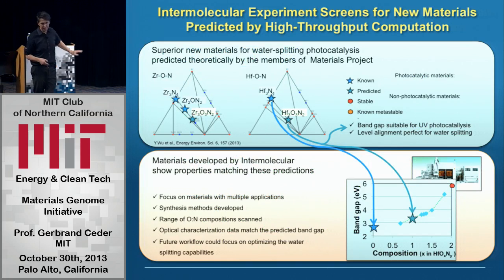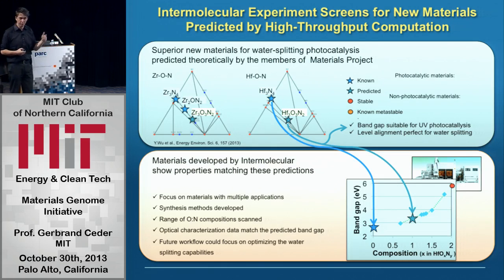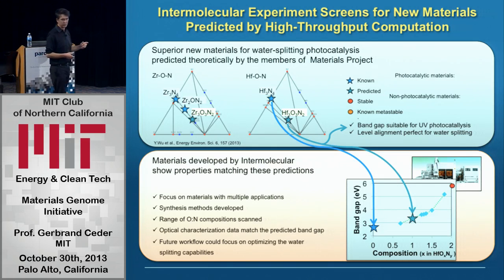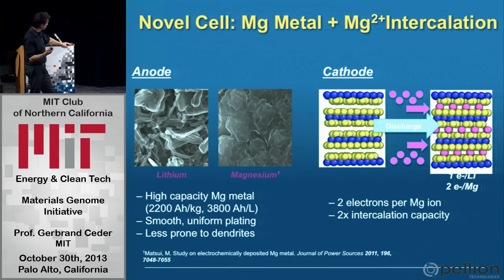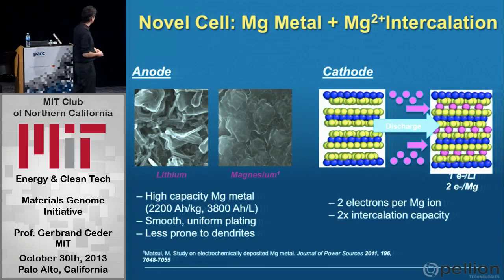There has been a lot of data in the Materials Project on photocatalyst materials, so things for water splitting. With these materials, you typically want to reduce the band gap of known photocatalysts, which are mainly oxides, so you can absorb more light. We put a bunch of predictions in there for oxynitrides, and Intermolecular has actually made some of them. The bottom graph shows the agreement of band gap between the theory and the experiments, which came out quite nicely. My own startup company, Pellion, uses this extensively.